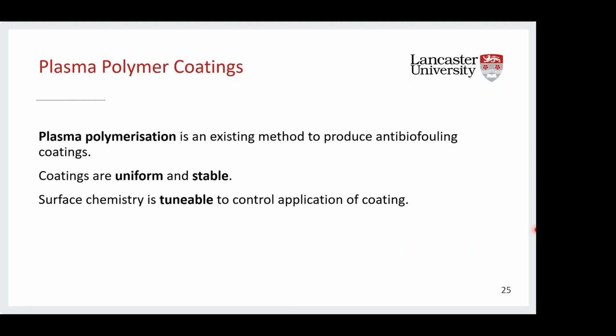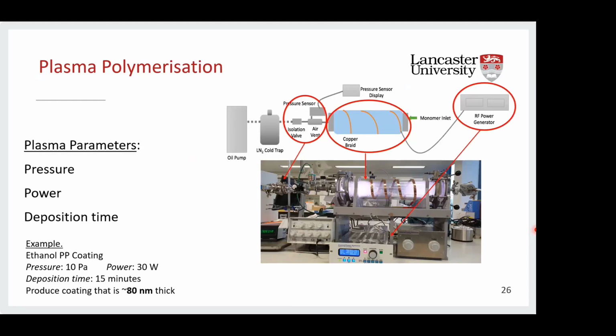Plasma polymerization is also benefited by the ability to control plasma parameters, and this allows you to tune the surface of your material for various applications. So in our work, the coatings are obviously geared towards anti-biofouling. And I would like to actually just state here that any material that you have can technically be used as a substrate to plasma polymerize onto, but in our case we use clean silicon wafers, and this is just selected for ease of the sample analysis.